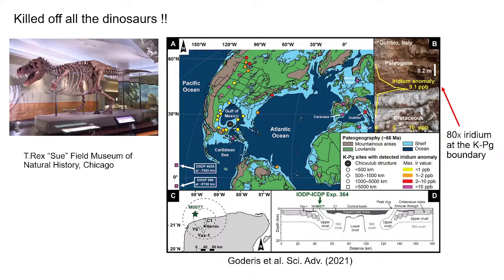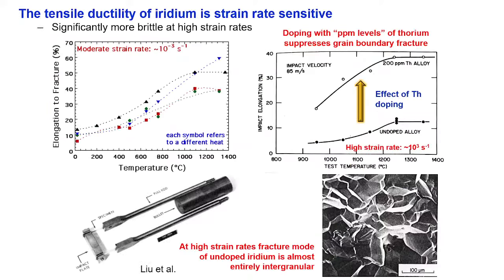Okay, so with that background, iridium is an interesting metal because unlike most FCC metals, it shows a ductile brittle transition. So if you plot, this is at slow strain rate, so 10 to the minus 3 per second strain rate. It shows somewhat decent ductility at room temperature, but then the ductility improves dramatically as you go to high temperatures. This is unusual because most FCC metals will be flat like this, right? Most FCC metals don't show a ductile brittle transition, so this is more like a BCC metal. But when you change the strain rate from 10 to the minus 3 to 10 to the plus 3 per second, so 6 orders of magnitude change in strain rate, this is what happens to the ductile brittle transition.